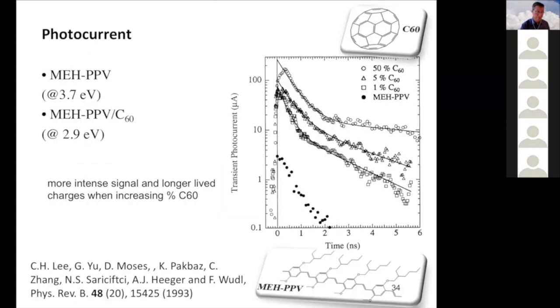You can also do photocurrent. Photocurrent is basically current that is generated by shining a light. From these experiments, charge transport is proven. If you increase the content of the fullerene up to 50%, then the charge can move through the film because the photoconduction transient has a very long lifetime. So the charges are very long-lived when you increase the concentration of fullerene. This implies that charges can move through the fullerene phase to the other electrodes.